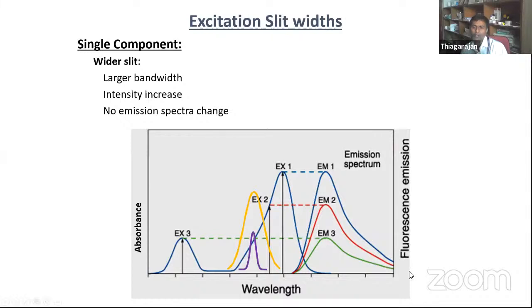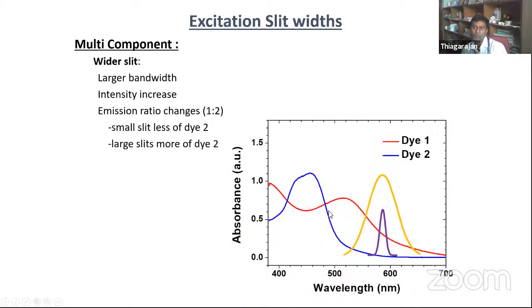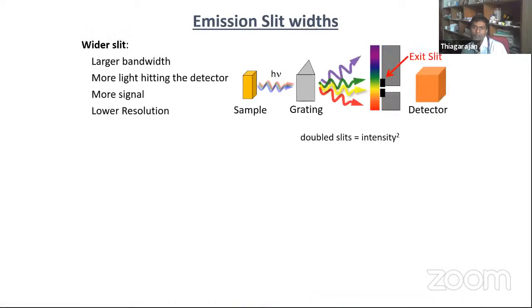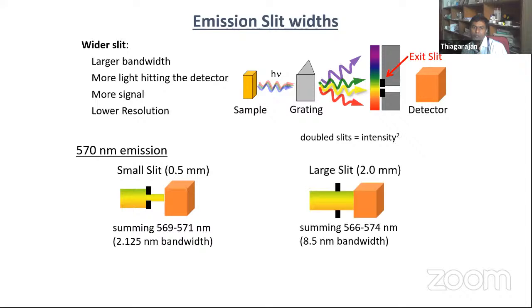With the wider slit width, you can see emission 1, emission 2, emission 3. When we increase the slit width, the emission intensity also increases. At the same time, you see the full width at half maximum also increases. You see the small slit width. It depends. The bandwidth is only 2.1. Here you see the 8.5 nanometer.